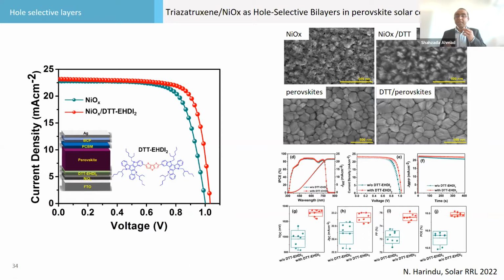And similarly, not only this, we thought the perovskite crystallization was better, because this is normal perovskite, and on triazatruxene, they show larger crystals. So the crystallization process becomes slower, and the perovskite yielded a bigger size of crystals here. And this is the device statistics, and so we also achieve close to 20% efficiency here with higher stability in this case.